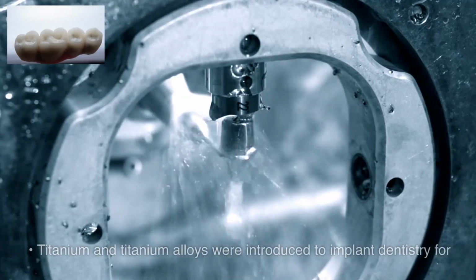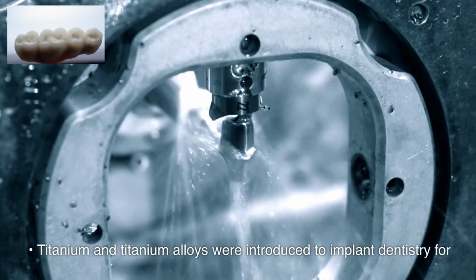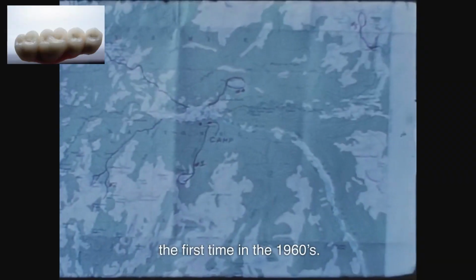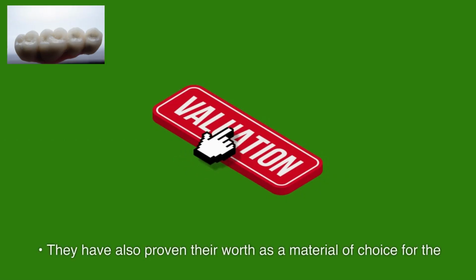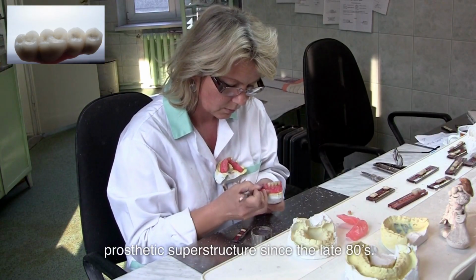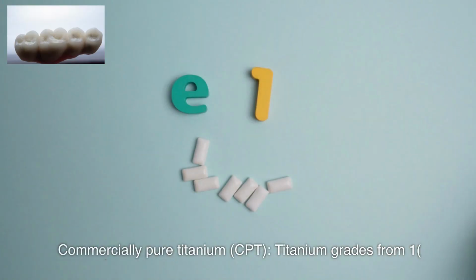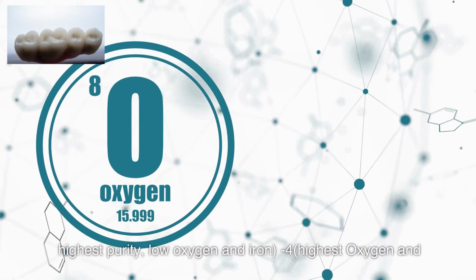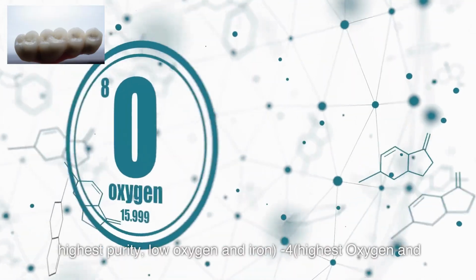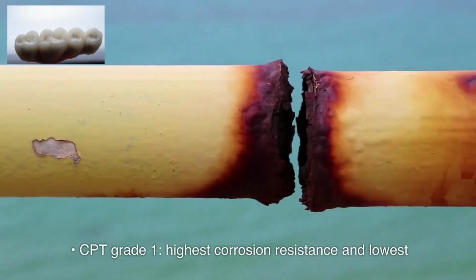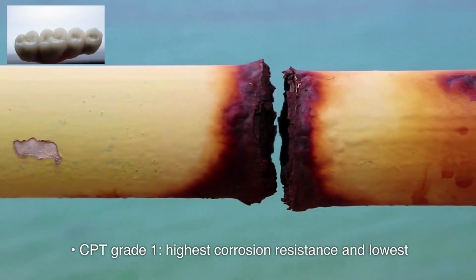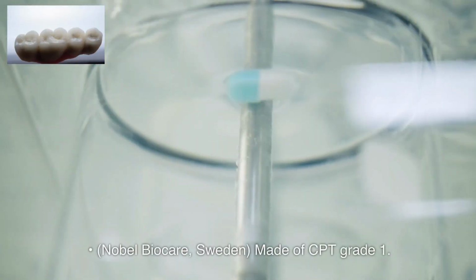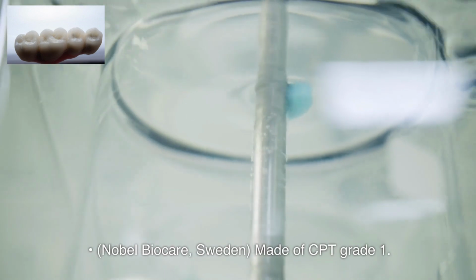Dental implant materials. Titanium. Titanium and titanium alloys were introduced to implant dentistry for the first time in the 1960s. They have also proven their worth as a material of choice for the prosthetic superstructure since the late 80s. Forms of titanium. 1. Commercially pure titanium, CPT, grades from 1, highest purity, low oxygen and iron, to 4, highest oxygen and iron. CPT grade 1 has the highest corrosion resistance and lowest strength. Nobel Biocare, Sweden, is made of CPT grade 1.